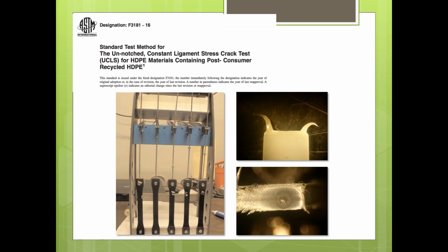So through the research report, there is a test now, an ASTM test F3181, that was developed specifically for testing and identifying that crack initiation through propagation phase of utilizing post-consumer recycled HDPE. Basically, they created very large wishbone samples. There's 3 test setups that are done, which we'll talk about a little bit, with 5 samples per run. And on the right side, you can actually see when eventually the wishbone samples are pulled for a certain amount of time with a certain amount of loading, what a piece of contamination looks like in the recycled resin and how that starts a crack and how that propagates across the sample itself.